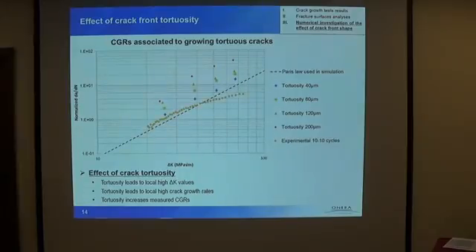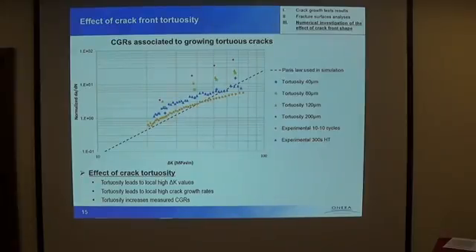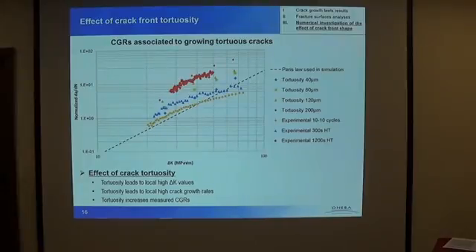If we compare this to some experimental results, here we have, let's say, a 10-10 cycled experiment. This fits the Paris law used in the simulation. If we now compare this to the 5 minute hold time cycles, we have an increase in the crack growth rate, and you can see that it matches pretty well with, let's say, 40 or 80 micrometers tortuosity amplitude. And if we compare this with 20 minute hold time cycles, the crack growth rate fits pretty well with 200 micrometers tortuosity. So we are able to match experiments and simulation.